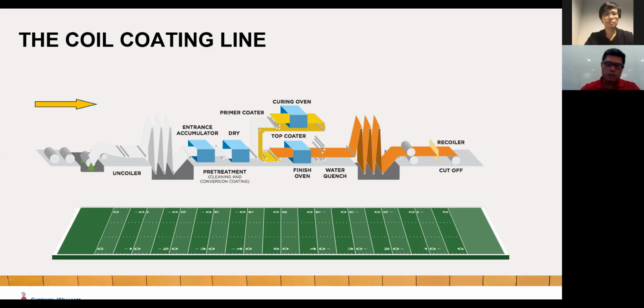The line speed here can range from 30 meters per minute to about 220 meters per minute. It depends on what substrate and how the line is designed. So the speed is very fast, and it's 24 hours operating, continuous coating. At the end of the recoil, all colors are already applied and cured. So that's the process.